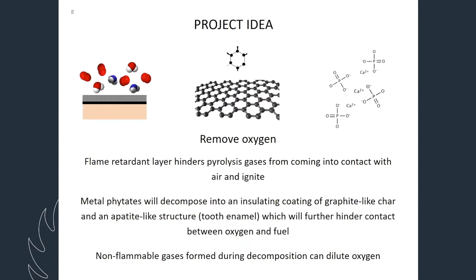And we also want to remove the oxygen. So this flame retardant layer will hinder the pyrolysis gases from coming into contact with the air and igniting, because they cannot penetrate this layer. But when this metal phytate layer decomposes, when it's heating, then the parts that form will form another layer. So the carbon rings in the middle of this phytic acid molecule will fuse together into a graphite-like polyaromatic carbon layer, the char.